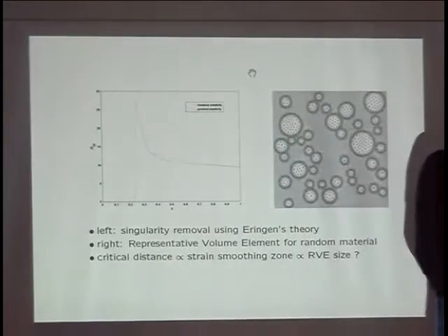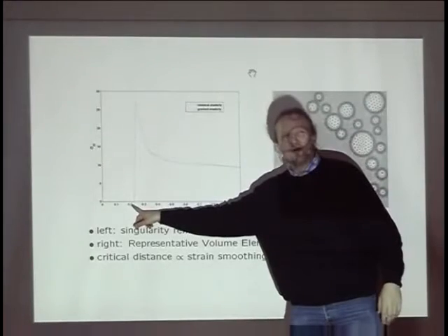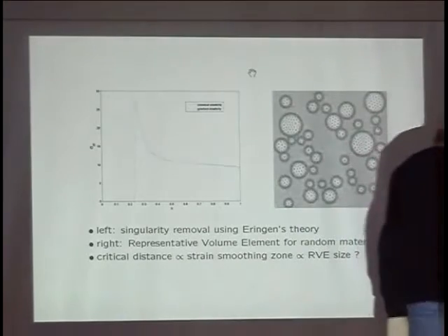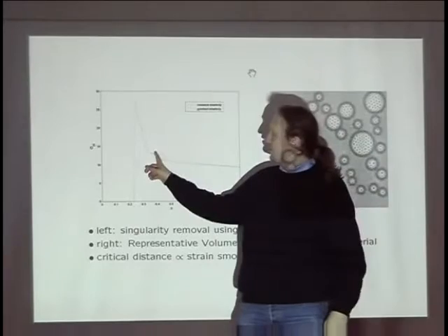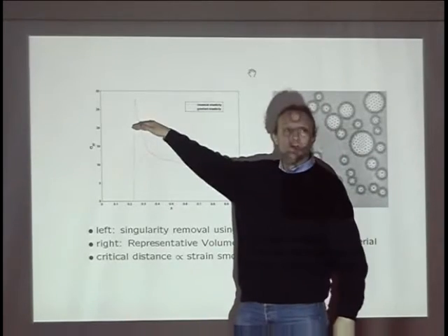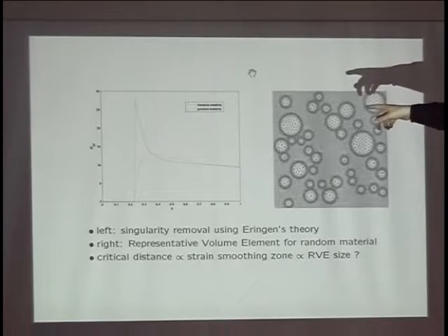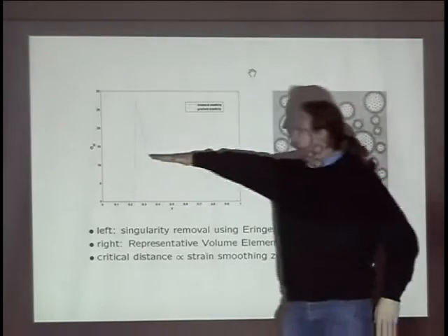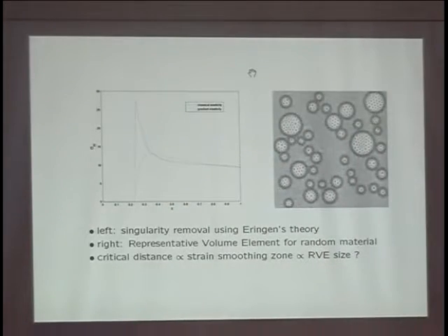Sorry, I'll start again. At the moment, my crack is in this unit 0.25. My length scale is 0.1. If I make small L smaller, the maximum will shift back to where it was before, and it will also go up. And you can really recover classical elasticity by letting L go to 0. So it's really a smooth transition from one to the other. And if I make L massive, I'll just get a flat curve with a bit of transition in the beginning.